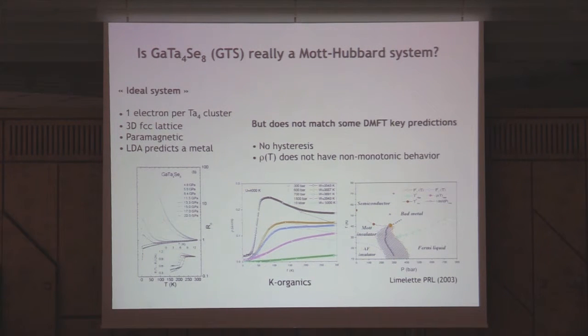And now, of course, I look at that with a lot of care, and I see there are some stuff that I don't like. The stuff that I don't like is that as a function of pressure, this thing continuously goes into the metal. So this doesn't show any sign of hysteresis, which is one of the hallmarks of V2O3 and what made DMFT so popular. On the other hand, close to the transition, where you go from insulator to metal, there should be this non-monotonic behavior that has been predicted and validated in organics or even V2O3, very close to the transition.